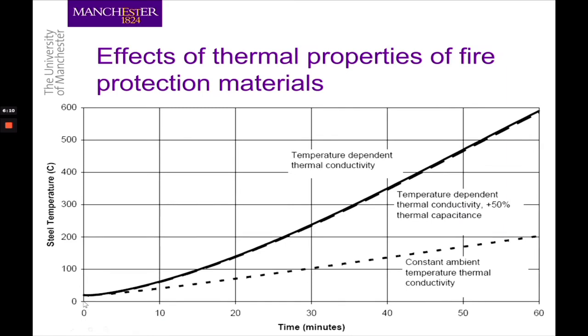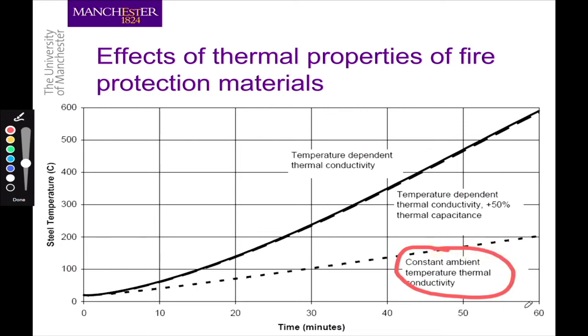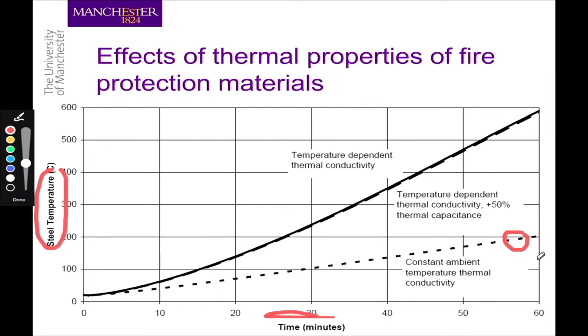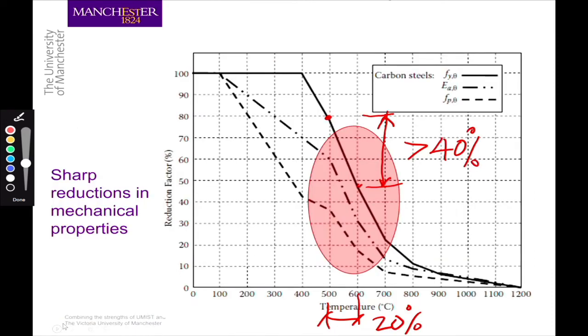So how bad could the situation be? What I have done here is use the temperature calculation equation in the Eurocode for protected steel. In one case, I assume that the material thermal properties are constant at ambient temperature. In the other, I change the thermal properties of the material, especially the thermal conductivity, as a function of temperature. So you can see here that this piece of steel has a totally different temperature-time response. Without temperature dependent thermal properties, after 60 minutes I get about 200 degrees. But if I include temperature dependent thermal conductivity of the material, I get 600 degrees. Totally different results.